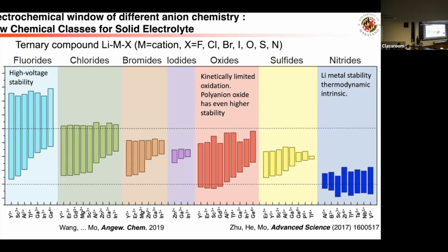And another thing is that the moisture stability is also very poor. Air stability is very poor, so that's also an issue. It's probably also one of the first. There's a lot of early research from the 70s on lithium nitride, without the metal. But now it's still used as the anode.